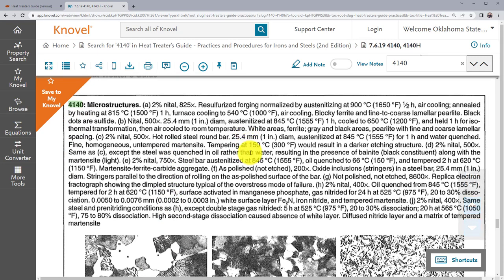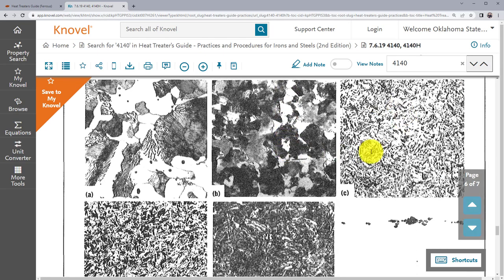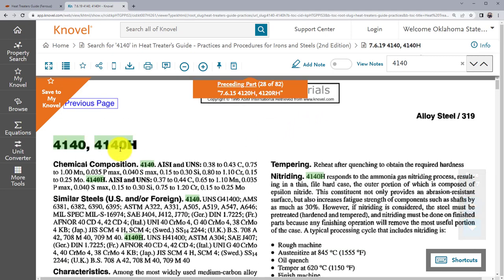The other thing we have is what happens if we come in and quench this. Let's look for one that's been heated up and quenched. Here we have C right here — it's basically been austenitized and then water quenched. We don't normally like to water quench 4140, but we're going to look at it. It's going to have untempered martensite — long and needle-like, white feathery. Here's our white feathery structure that we would expect to see as a fully quenched structure. Using the Heat Treaters Guide is going to be a great source for you to look at the different alloys and what structures you're going to have. You can get the Jominy data and the anticipated structures. Each steel will have a page in the same format. We'll see you in lab.